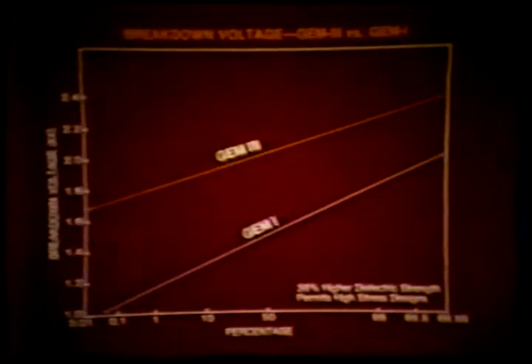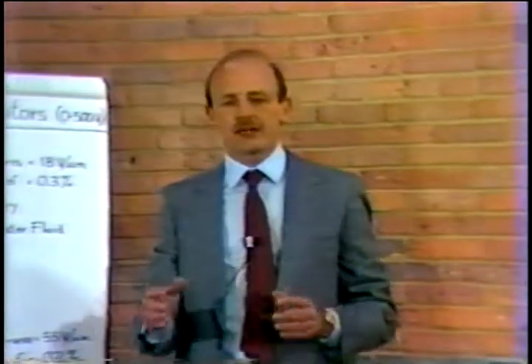Here we see a comparison of the effect of the high resistivity Gem 3 electrodes compared with the lower resistivity Gem 1 electrodes. The breakdown voltage is plotted as a function of the percent survival. We see that the Gem 3 electrodes provide approximately 36% higher dielectric strength than the Gem 1 electrodes. I believe this is a classic example of how understanding failure mechanisms can lead to improvements in capacitor technology.